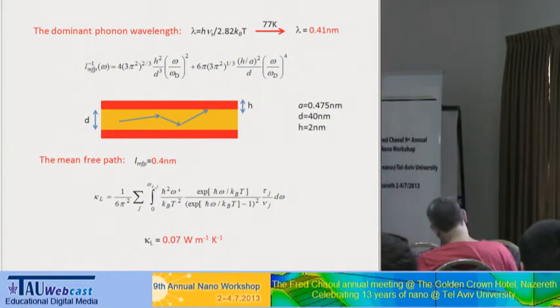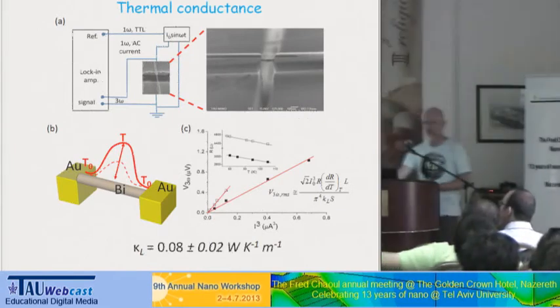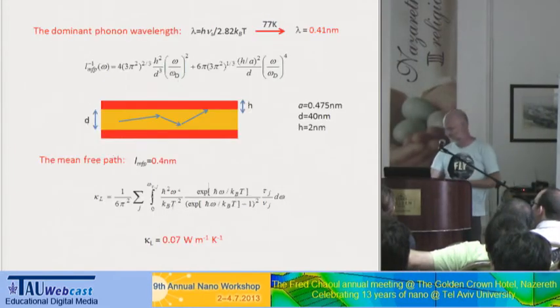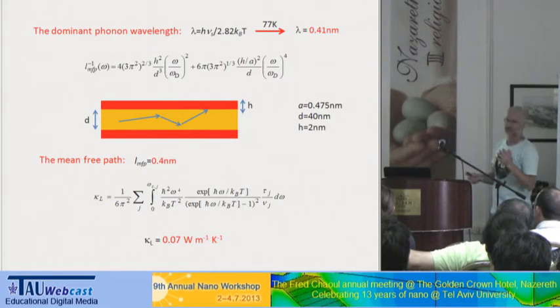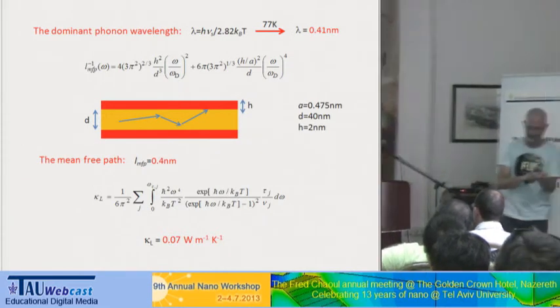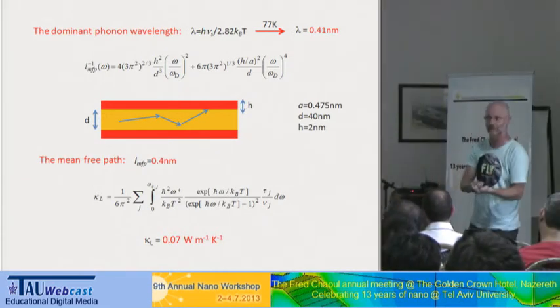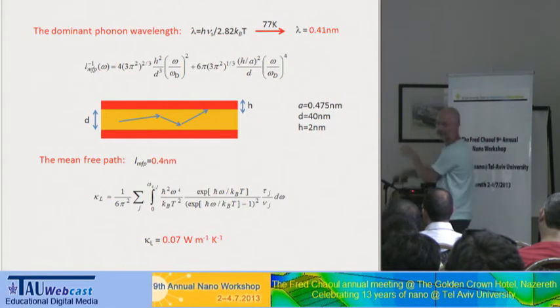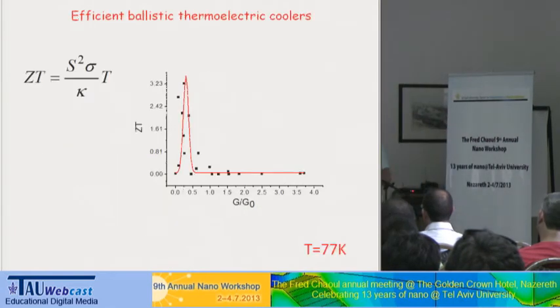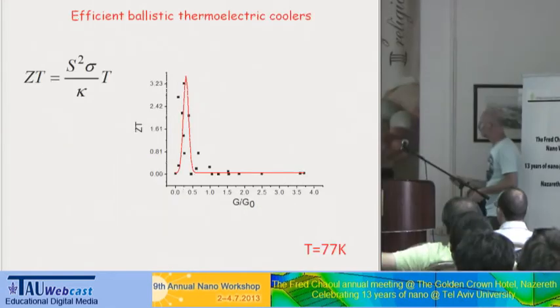Experimentally, what we measure is 0.08. So that is quite nice. So now we have everything. We have the Seebeck, we have the electrical conductivity, and we have the thermal conductivity. All you have to do is plug them into the equation and see what we get. And this is what we get.